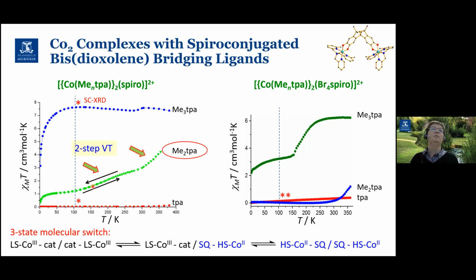This one, we can go up and down and cycle back and forth over that transition, and the higher temperature step is associated with solvent loss. So that one tends to change as we heat it up too far. But essentially what we believe is happening in this complex is that the first transition corresponds to switching at one half of the dimer, and then the second step corresponds to switching at the second half of the dimer. But when we go to the bromo Spiro, things are a little bit different.